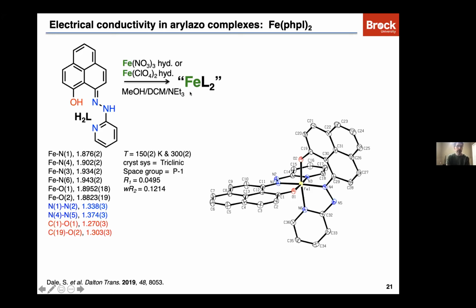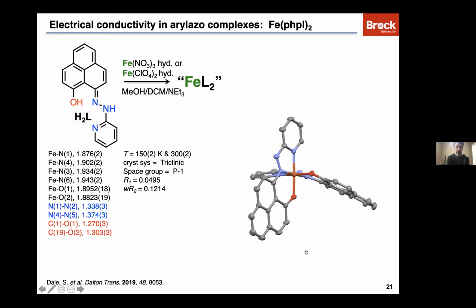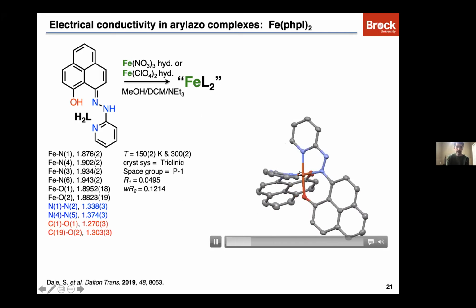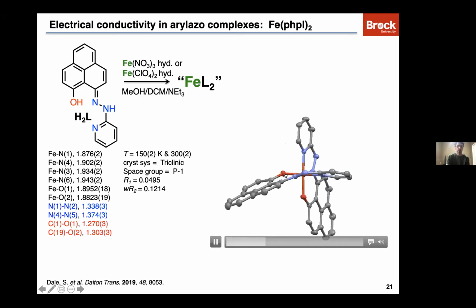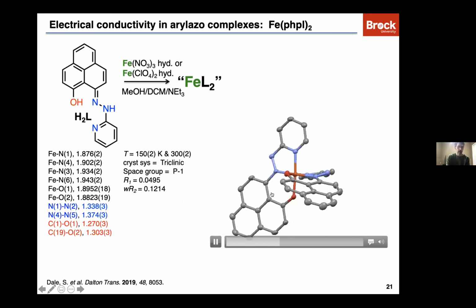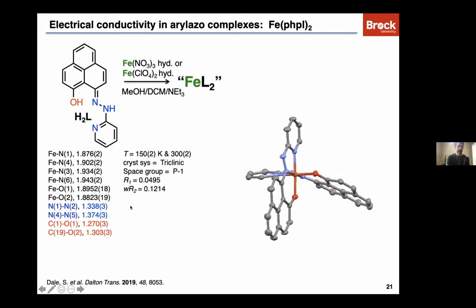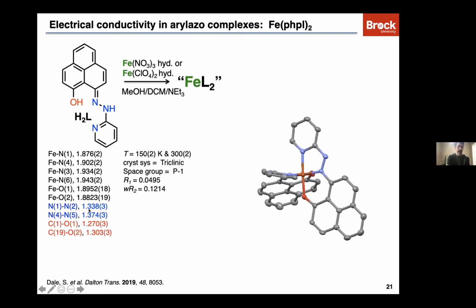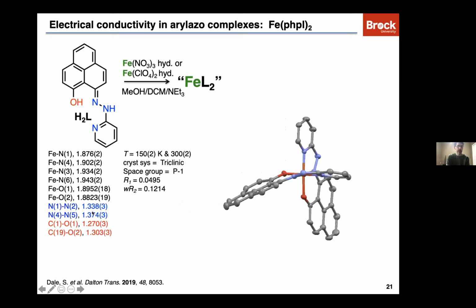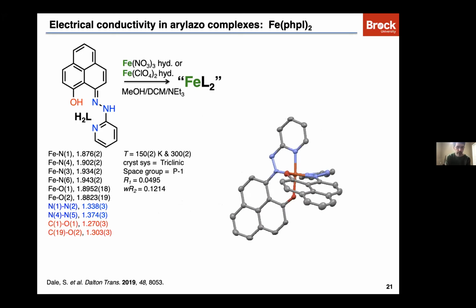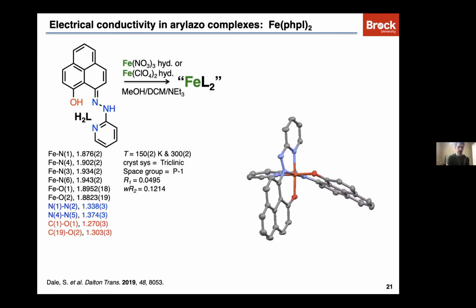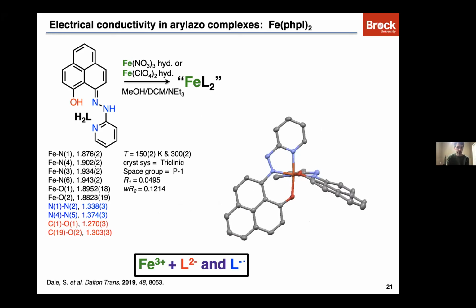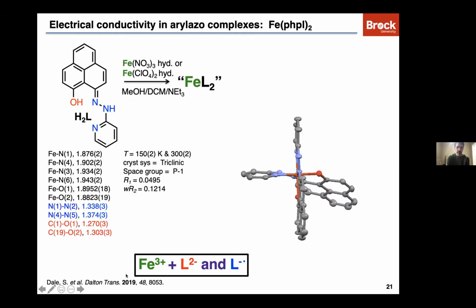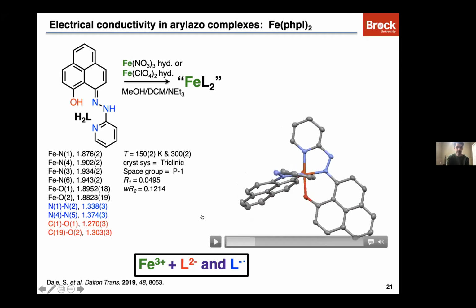It's unclear what the oxidation state of the ligand is, but if you rotate the structure around, you can see that the ligand is kind of in 2 forms. One is planar, one is kind of floppy. And what we actually have are 2 very different ligands. So one ligand is in the dianion form, the other one is in the anion radical form, and we have iron in the +3 oxidation state. So we have a ligand mixed valence system in this complex.